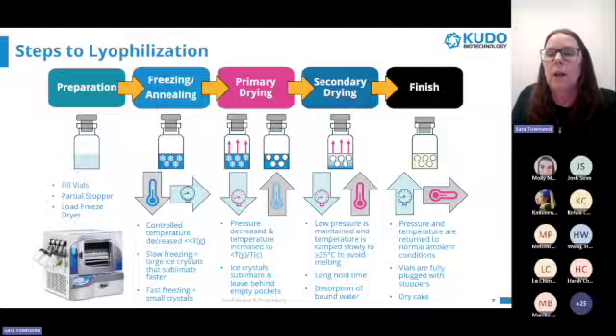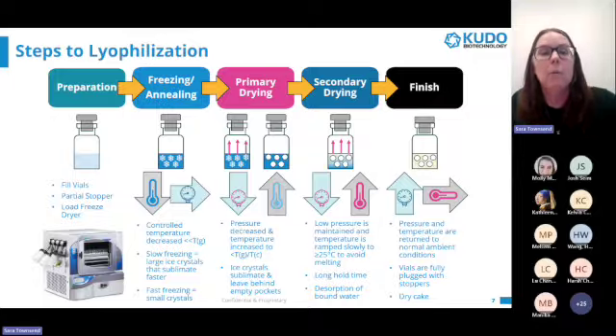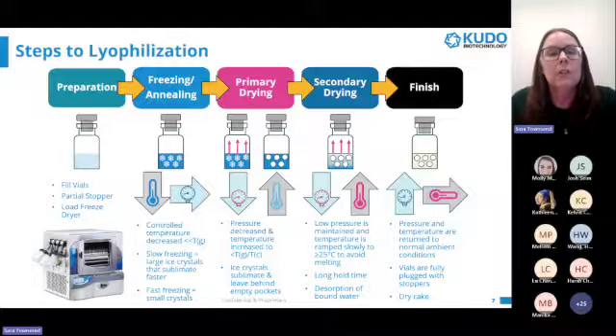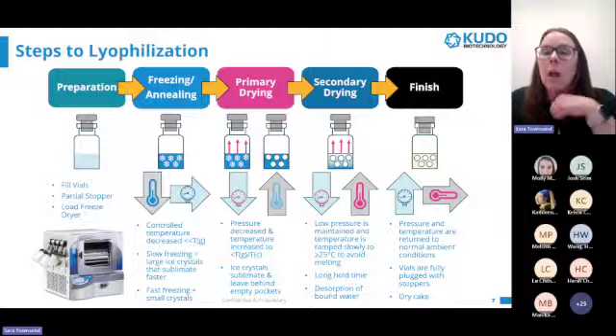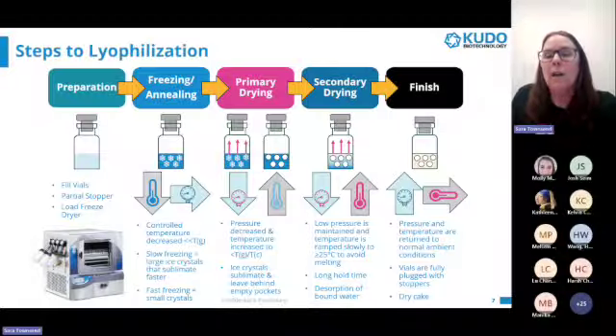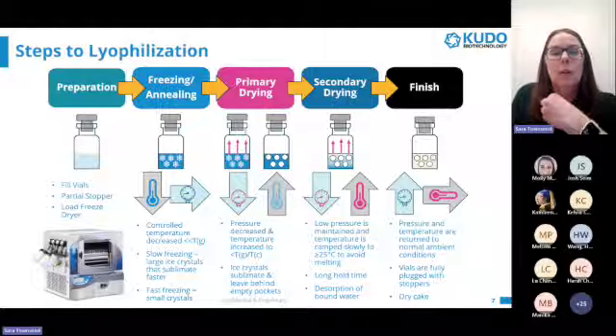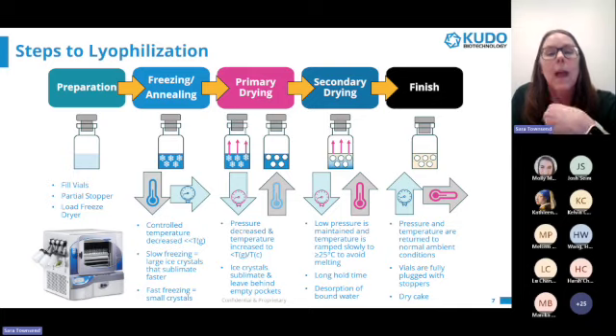For secondary drying, the low pressure is still maintained, and you may even lower it a little bit more, and the temperature is slowly ramped up to room temperature or above to avoid melting. Note that increasing the temperature to well above room temperature will shorten the drying time but could cause degradation of the drug product. This step tends to have a very long hold time, and what happens during this step is the desorption of bound water.